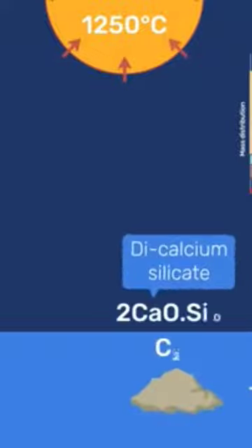and two things happen. First, the aluminates form a liquid phase that can be seen as a solvent for high-temperature reactions. Second, a reaction between C2S and additional calcium oxide takes place to form tricalcium silicate, 3CaO.SiO2, or C3S in cement chemistry. This phase is the most important one in Portland cement. Its impure form in industrial cements is called alite.